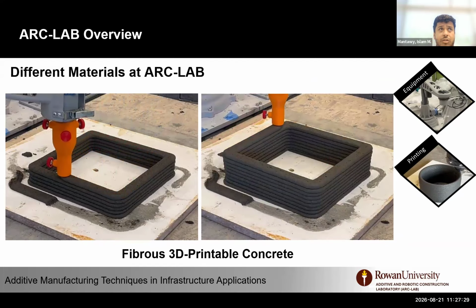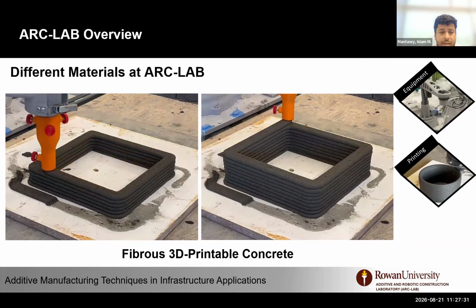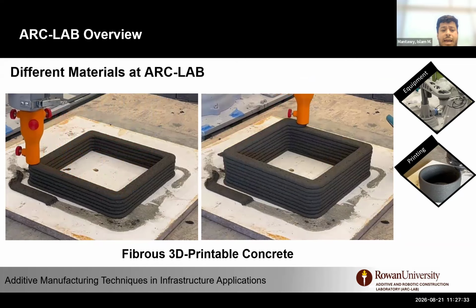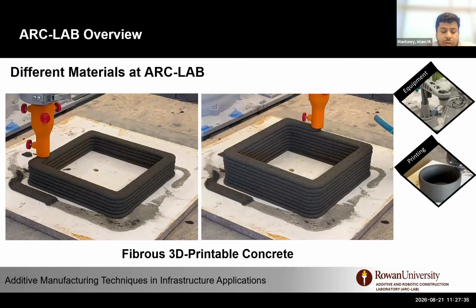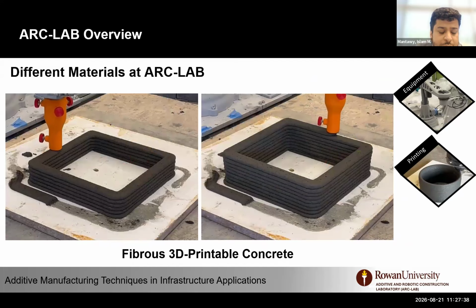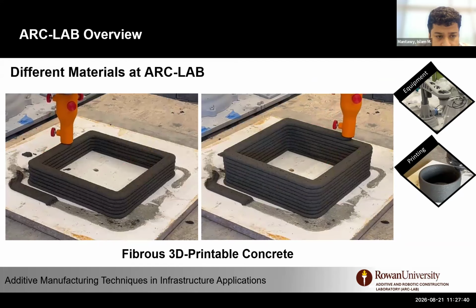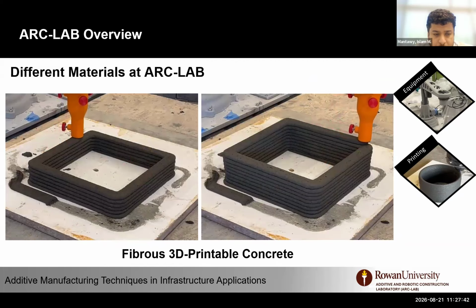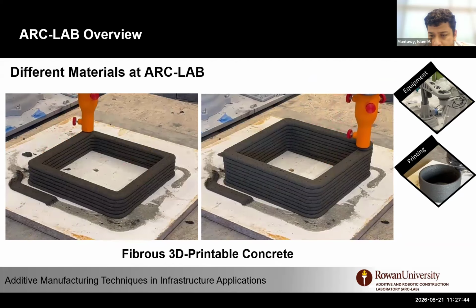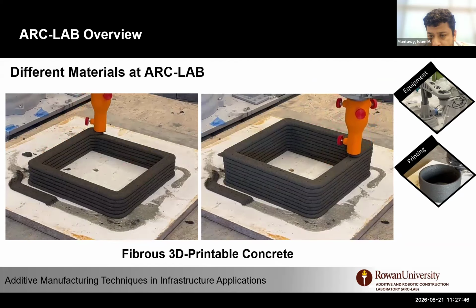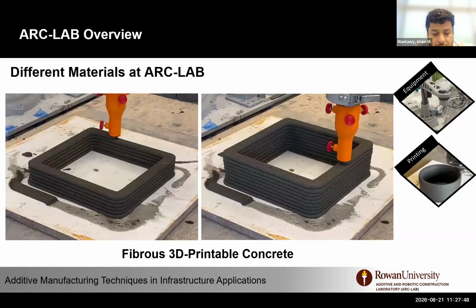Our mixes range without fiber around 10 KSI as cast. We're going to drop it a little bit once it's printed, by about 20%, so around 7 to 8 KSI without fiber. With fiber, you can increase 2 to 3 KSI, and it actually has benefits in the flexure capacities too.